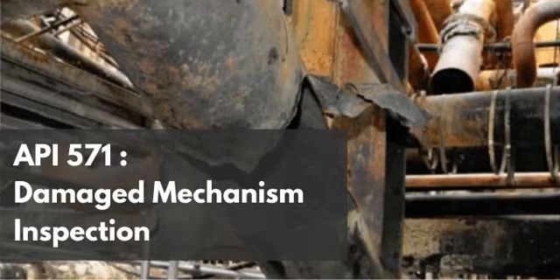Right, because stainless has the chromium. Exactly. We are relying on a robust chromium oxide passive layer that simply does not break down in the alkaline carbonate environment. So it just shuts the whole mechanism down. Completely. The electrochemical cell that drives ACSCC is completely neutralized by the chromium and nickel content in those higher alloys. The mechanism requires an anodic reaction that is specific to the iron matrix in an alkaline solution.